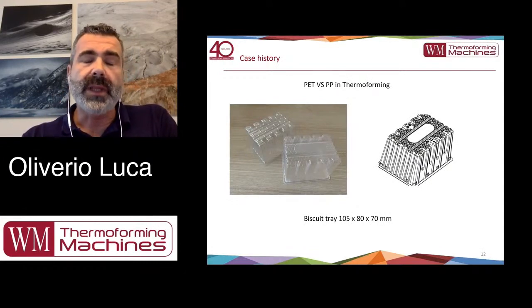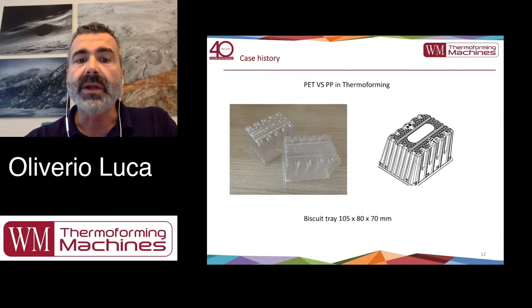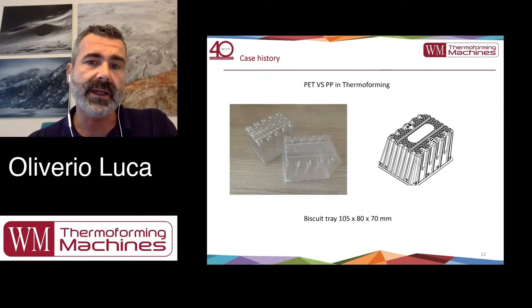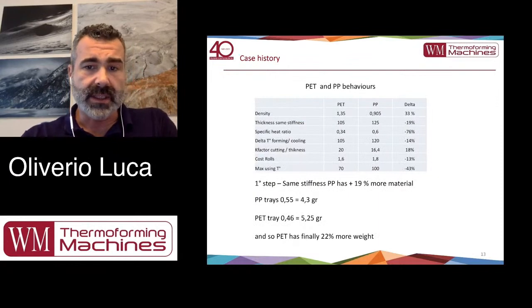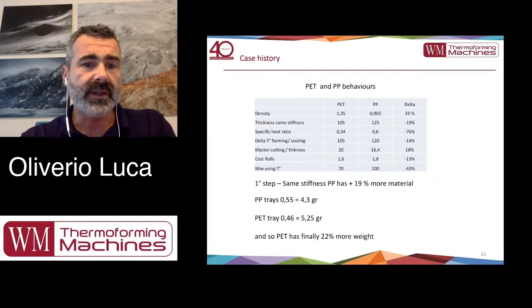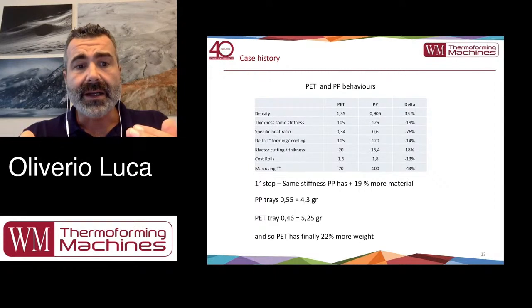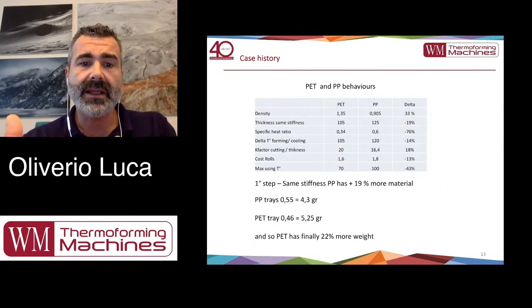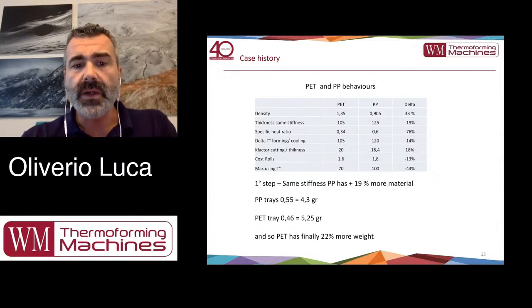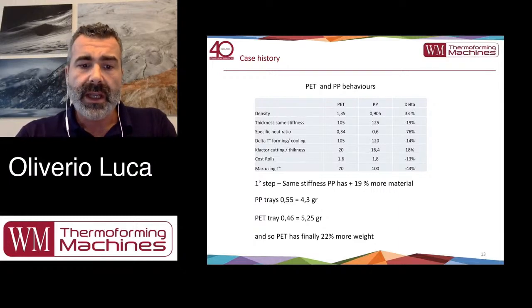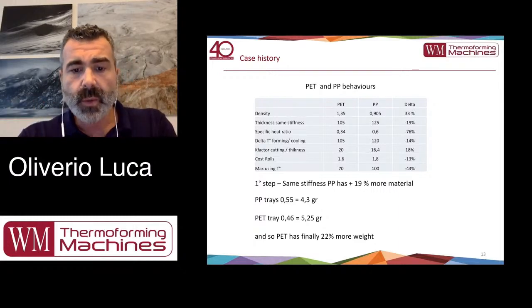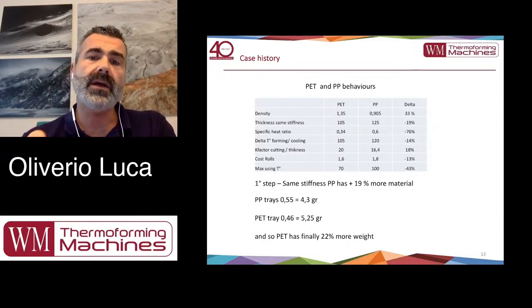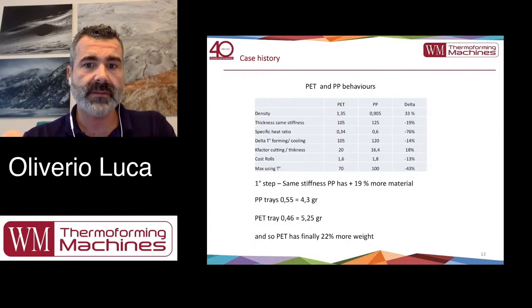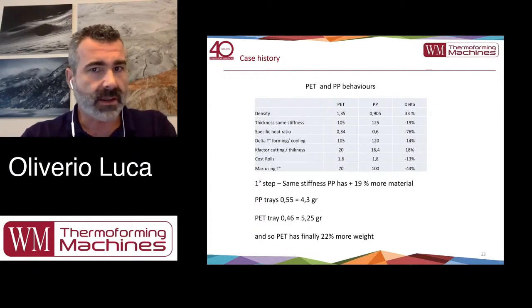When we are looking at thermoforming, most of the time we are producing PET and polypropylene, and how can we decide which material is better for this application? We have to study the behavior of the material. This one is an example, a case study. In this case, we can see how the density is completely different between PET and polypropylene. The relation between the thickness and the stiffness is completely different, and all the other characteristics. We worked it out, and we found out that for the same product we need 22% more weight in PET in order to have the same stiffness. And so we can say, no, PET is not okay for this application.